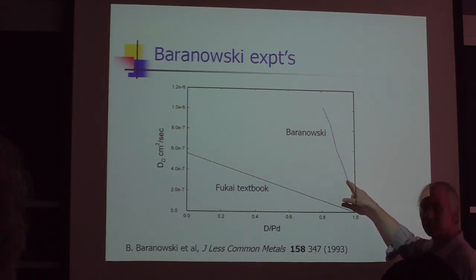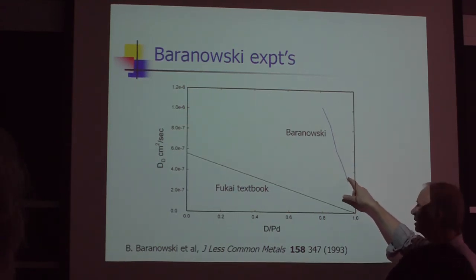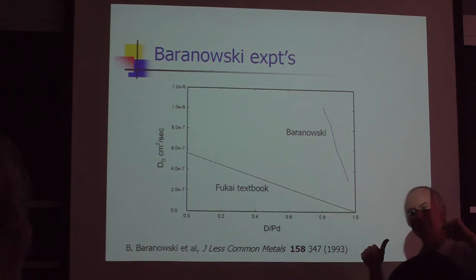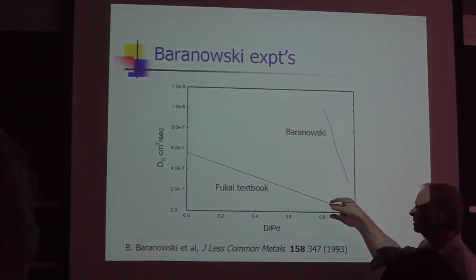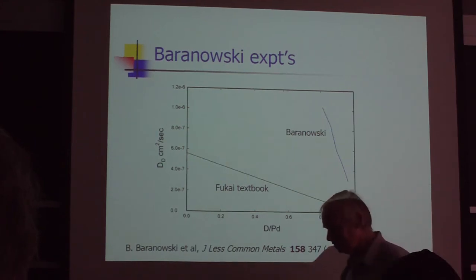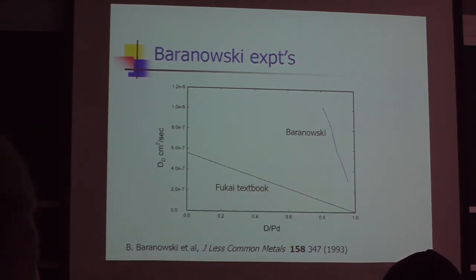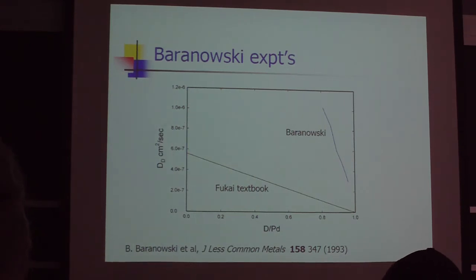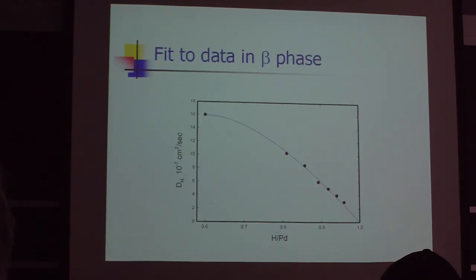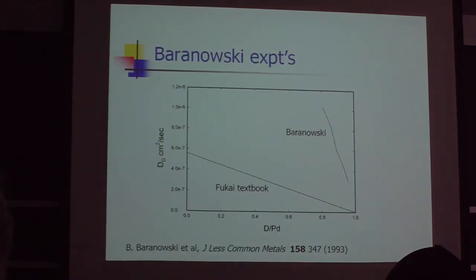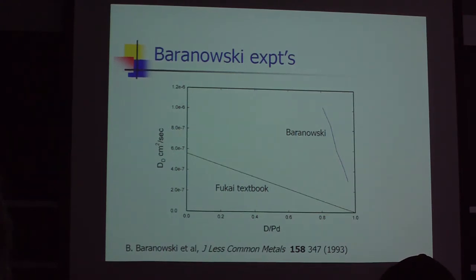Looking at the textbook value, you get a curve like this. But if you read the fine print in Wicke's book, it says it's only good for the alpha phase—the low concentration side of the miscibility gap. So the textbook value is only good at about 2% loading.